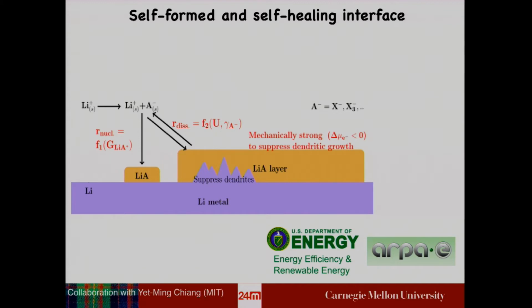One approach is simply, you have a growing wire. If you put something really strong, then you can block that growth. That's sort of the obvious way to do it. Unfortunately, it turns out that when you try and make a material that is hard, it does not allow lithium ions to move through as efficiently, so that remains a challenge. We've learned a second surprising way to do this, actually something that was inspired from geology, where in the context of